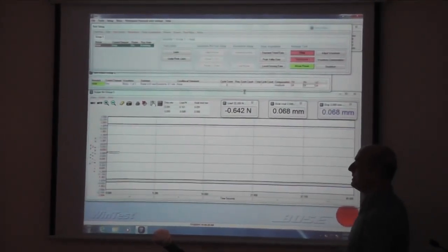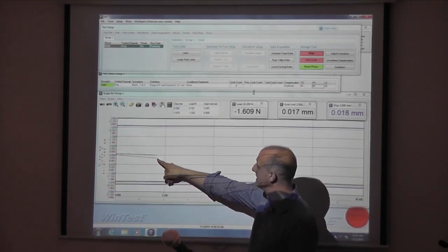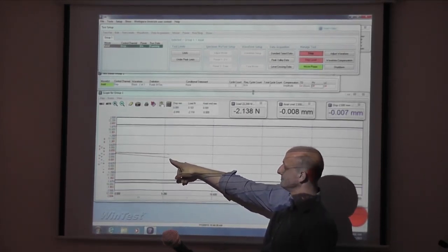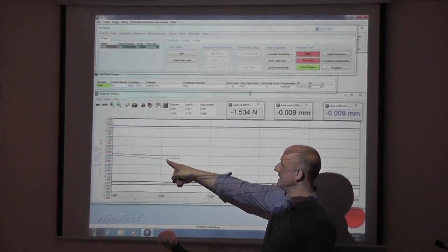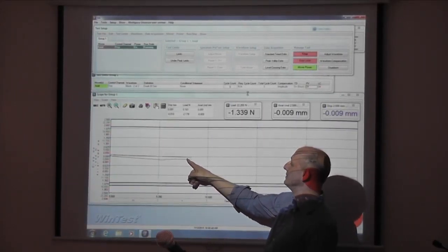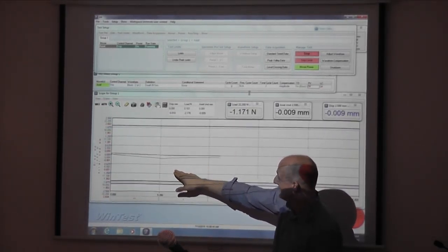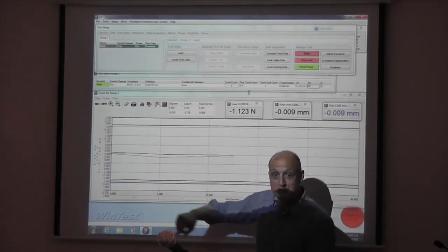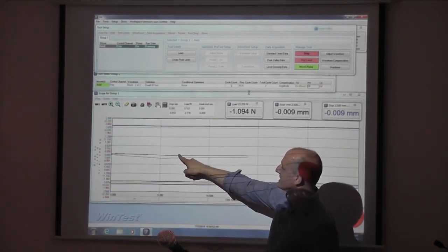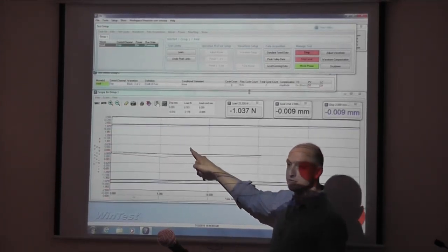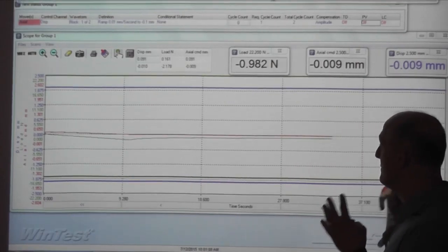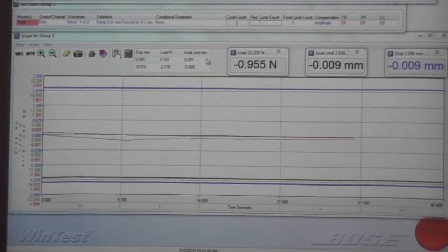So we're putting in a slow ramp, and this is the load increasing, increasing, and then it's relaxing off. That's the end of the ramp phase, and it's a slow relaxation. It didn't peak as much as the last one, so we've got our scales slightly wrong, but what I wanted to show is this relaxation phase. It's very, very dramatic, it's very, very quick.